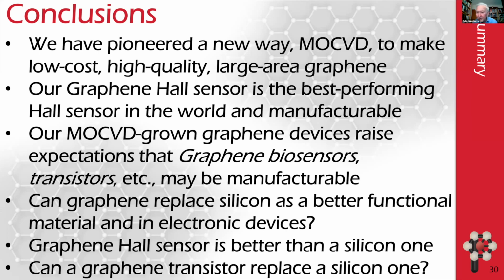Well, I'm going to put this to Harry in a moment, but I think it's a really good question, because we know that in metals and alloys and so on, the strength of those materials is largely controlled by the dislocations, right? And when you look at graphene, what the thermodynamics tells you is you're going to have point defects there, and may or may not have dislocations. And again, we need to do the electron microscopy. So the type of defect will certainly be important in controlling the strength of the graphene. But Harry, do you have some thoughts on this?